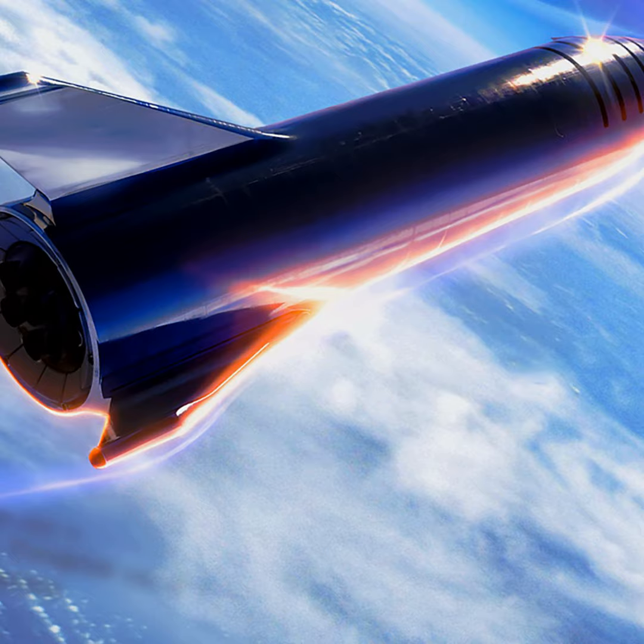So from the outside, it might not look too bad. The surface isn't burning away rapidly. Right. The actual mass loss rate is way lower, like 20 times lower than the surface scorch case. Visually from the surface, you might not see much alarming damage. But, and this is the twist, right? The researchers found this still leads to catastrophic failure. How? This is the crucial finding.